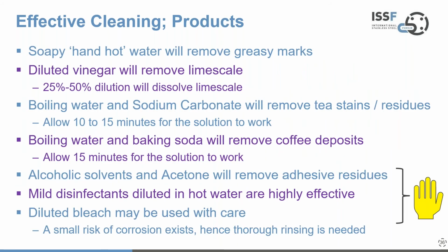But what about cleaning products? So here's a number of illustrations for different situations. For greasy marks, soapy water that's about hand hot will remove those greasy marks quite effectively. For lime scale, diluted vinegar, if you've got a 7% acetic acid vinegar, a dilution of 25 to 50% will dissolve lime scale quite effectively. If you're working with tea stains or similar residues, boiling water and sodium carbonate will work, allowing 10 to 15 minutes for that solution to be effective. And if it's coffee deposits, then you need boiling water and baking soda. Similar amount of time, about 15 minutes for the solution to work effectively.